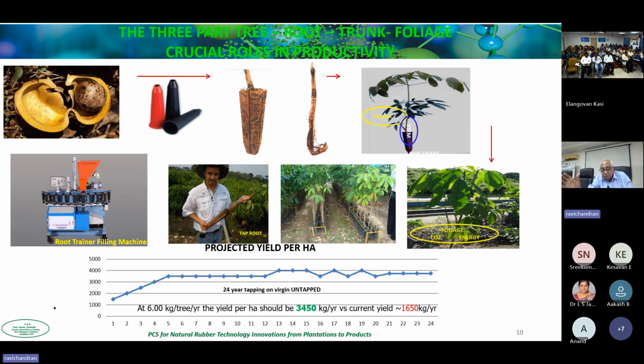Now this shows you the spectrum. You've got the rubber seed at the left, and those plastic things are what we call root trainers. We put coir pith inside and we put the seed, and then in these containers, the second picture is of a taproot. And then once the plant has grown, we graft the actual clone, which is going to yield, onto this first one, and we cut off the original plant on the left side. This is the original tree. We cut this off and allow the clone to grow.